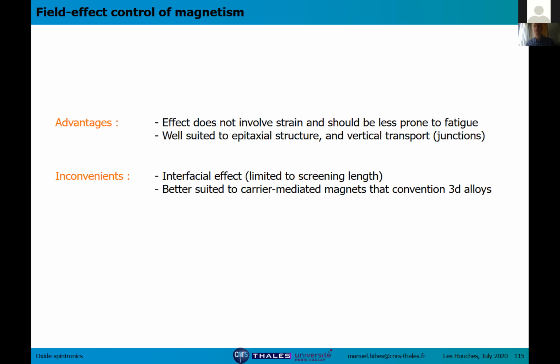it's the best approach. The inconvenience is that being an interfacial effect is also an inconvenience, because you need to work with very thin layers. And so far, it seems to work better with, well, it should be more applicable to carrier-mediated magnets, but so far the most spectacular results are with the 3D alloys. And I think there's room for improvement in this direction.